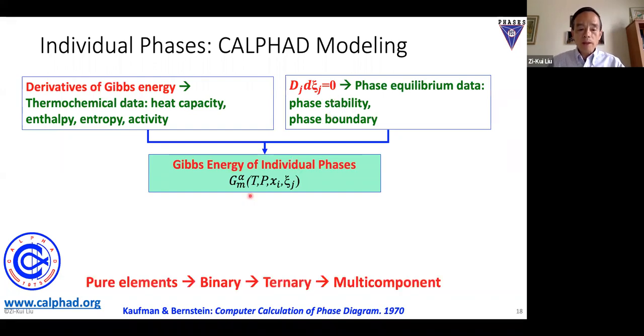You start with one pure element, you do the binary, you do the ternary, you do the multi-component. And today, the commercial databases, some of them have 20 or 30 elements for highly alloyed materials like nickel-based superalloys and steels, aluminum, manganese, and titanium alloys.